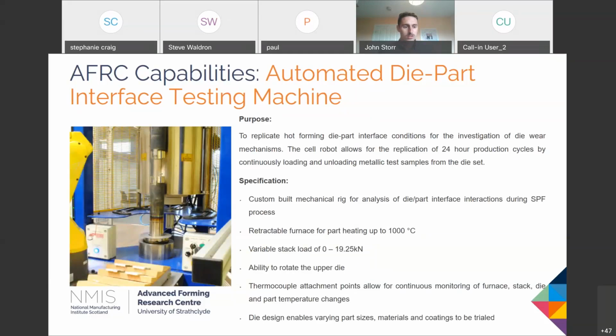So, as well as the larger scale pieces of equipment, we have a number of complementary pieces of equipment that I'll talk about just now. We have our automated die part interface testing machine. This is a unique machine that we had purposefully made for the AFRC. And what we're trying to do here is replicate die wear activities on a very small scale using small coupon samples. Automated so that multiple parts can be run to simulate a process such as would be done in a manufacturing setting. And then it will allow us to assess things like die wear, tool material, and assess also lubricants and coatings, so that then we can understand if perhaps a novel lubricant, a novel coating, or a novel die material would be suitable for the process.